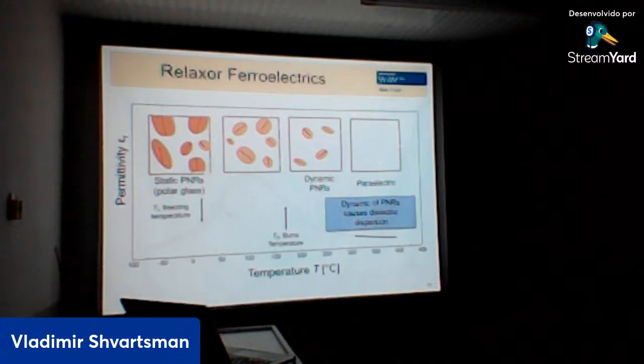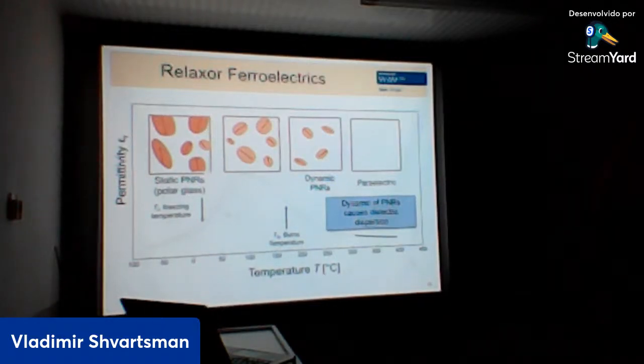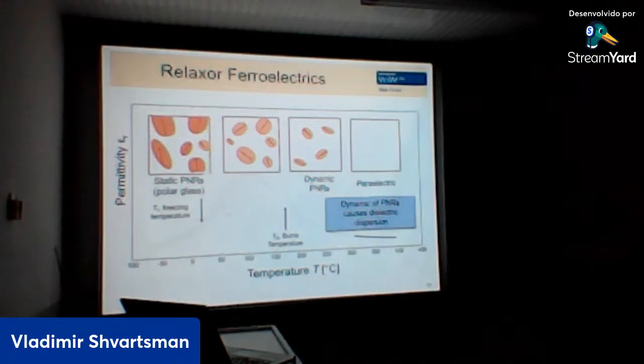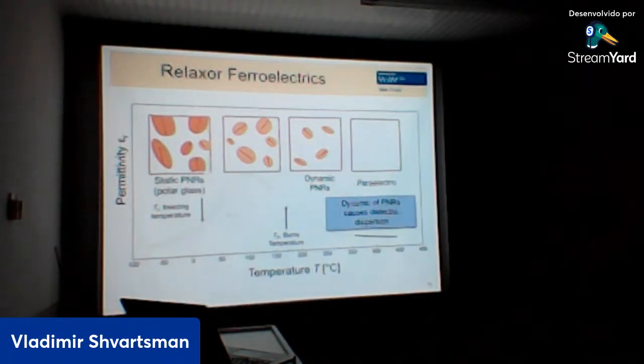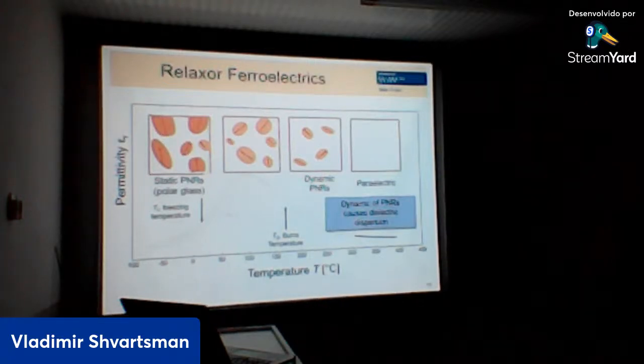So, at high temperatures, we have a paraelectric state without any correlation of the polarization. Then, on cooling, below the so-called Burns temperature, we observe the appearance of these polar nanoregions. Initially, they are dynamic. This means they easily fluctuate between different polarization directions. When we apply an electric field, we can align them all along the field and we have a large induced polarization. But when we remove the field, they go fast back to the disordered state. If some of you are from magnetism: in magnetism, similar behavior is called superparamagnetic behavior. Therefore, sometimes they call it superferroelectric behavior.